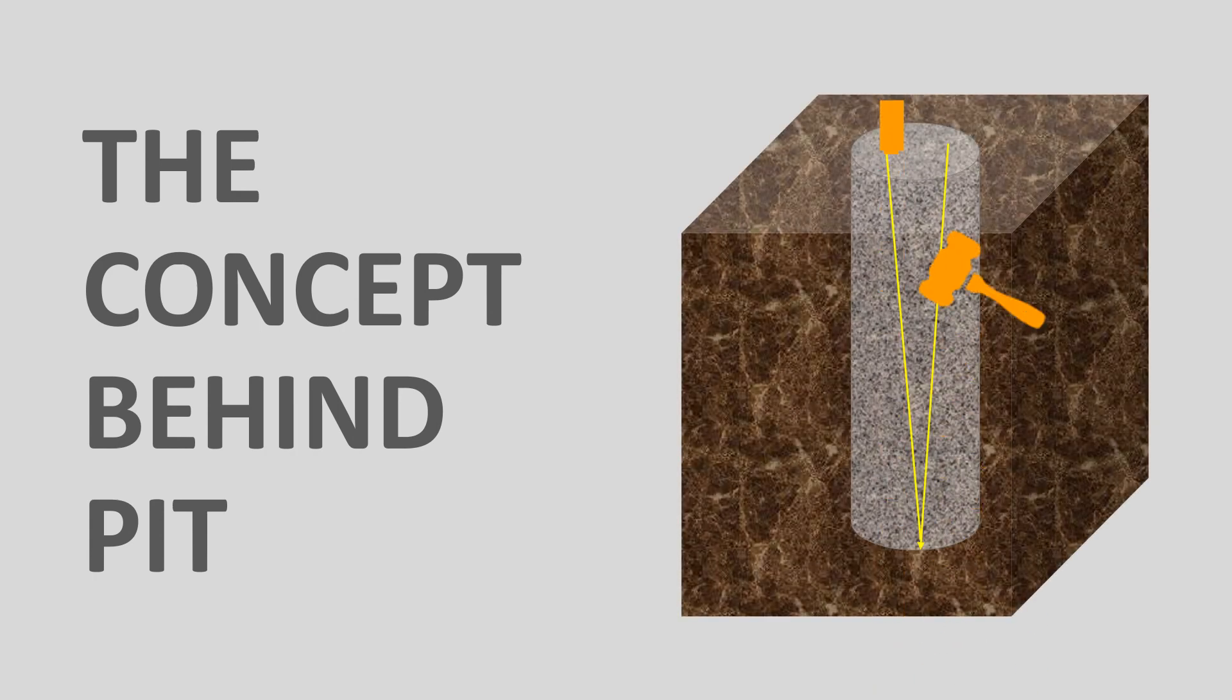The concept behind the technique is to apply a low strain impact to the pile head. The sonic echoes from the pile end are recorded and analyzed. This test should be conducted no sooner than seven days after casting or after concrete strength achieves at least three quarters of its design strength.